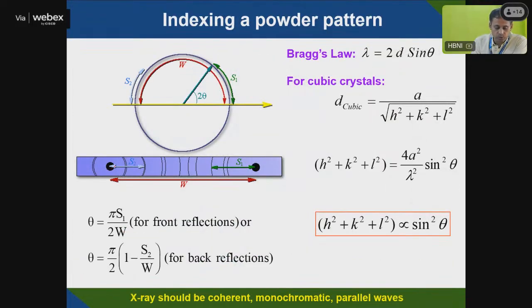So if you see these two rings here, and you know the arc length S1 and W is the length, then using this you can find theta by pi S1 by 2W, for the front reflection and back reflection. But this is based on the earlier powder X-ray diffraction, where you have a projector, and on the bottom you take a big graph paper and draw, and it takes more than 1 or 2 hours just to get a spectrum, which nowadays you get in 2 minutes, a very good spectrum.